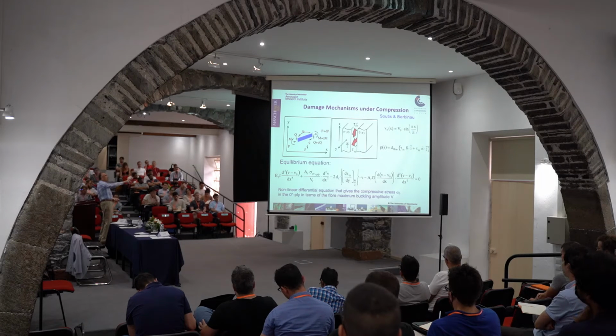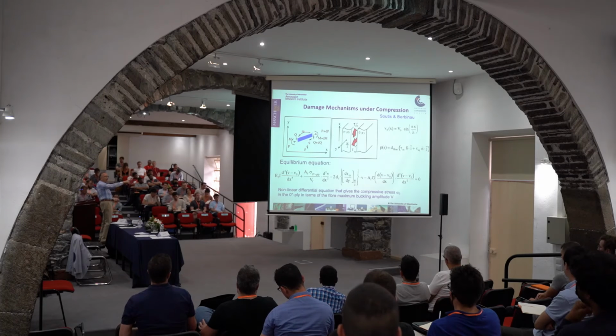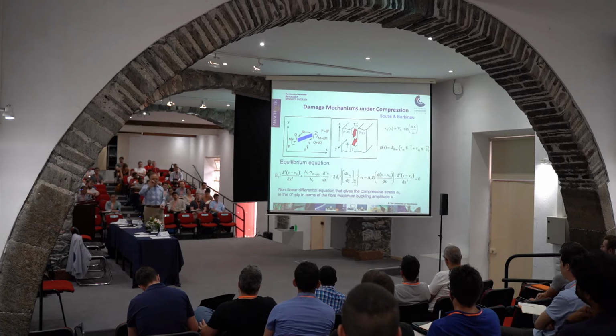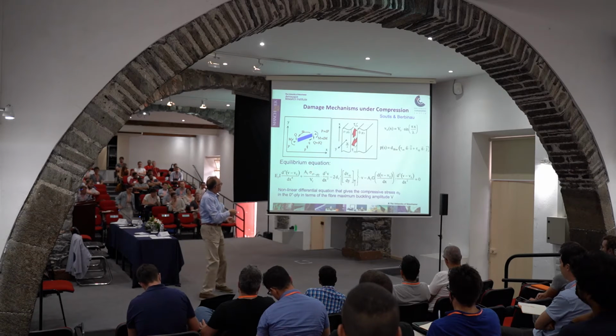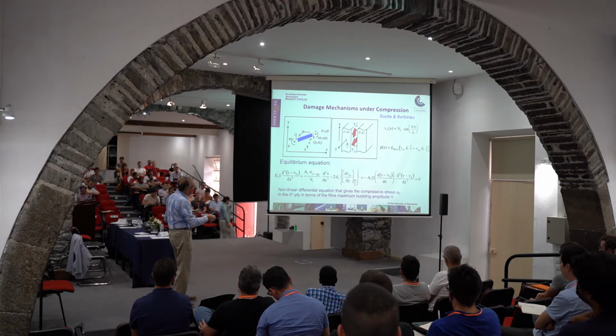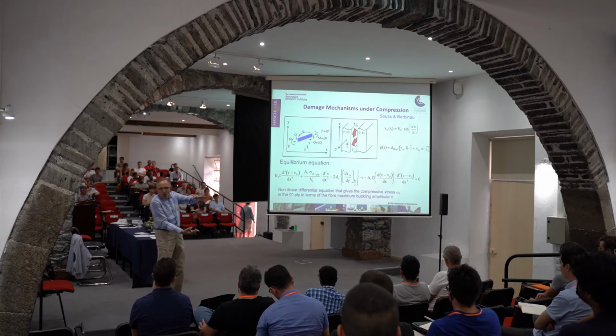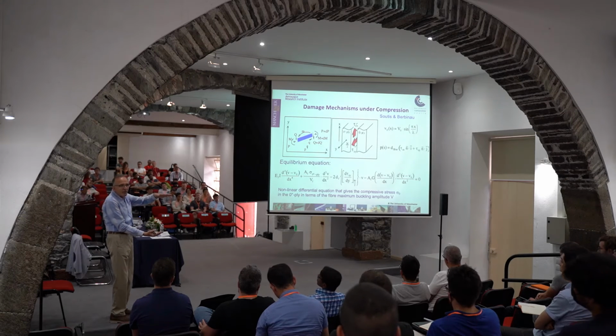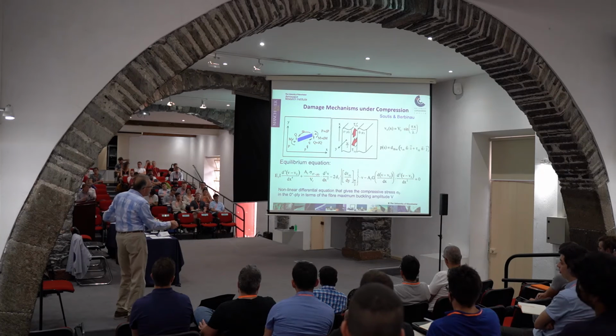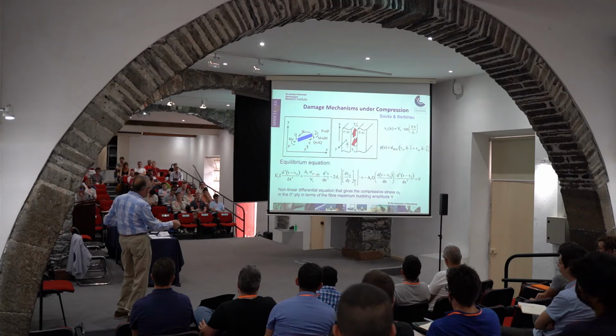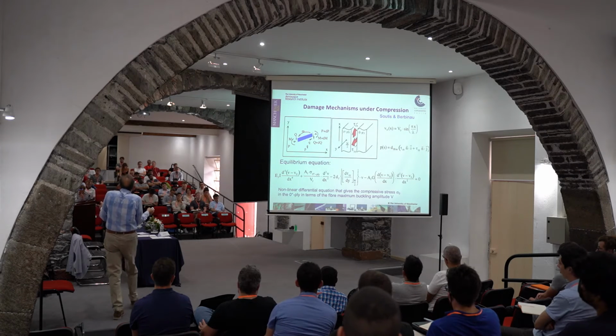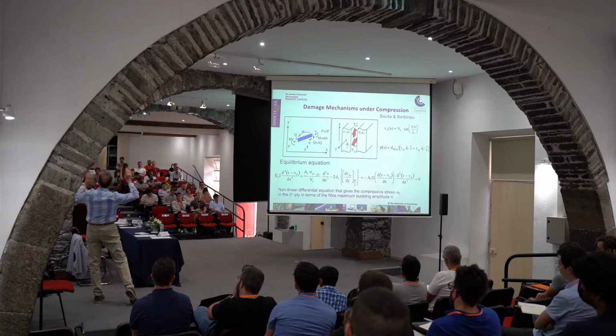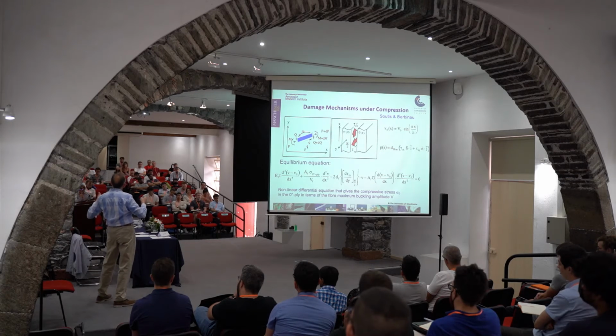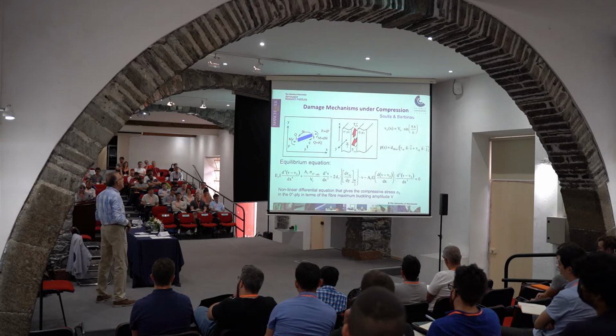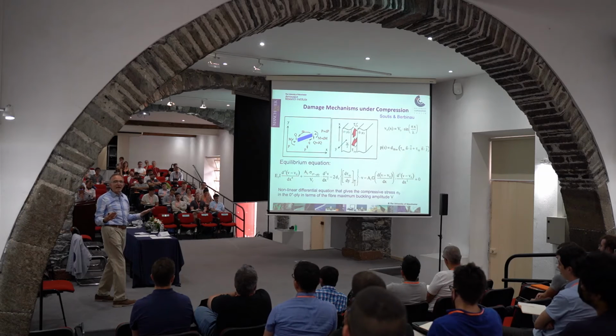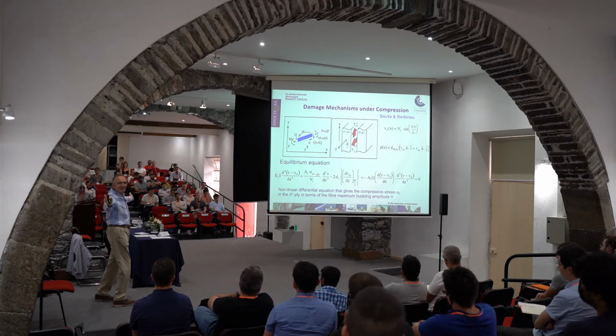And this is what we do here. Do you recognize that equilibrium equation, that final equation? It is a 4th order differential equation that when you solve, you calculate the stress in the zero ply that supports the axial load, isn't it? The zero layers parallel to the loading axis take all the stress. So you need to calculate this stress, sigma zero ply, and when it exceeds that 1600 megapascals value or 1800 megapascals value, depending very much on the compressive strength of that zero layer, then fiber micro-buckling will take place and the whole laminate will break.